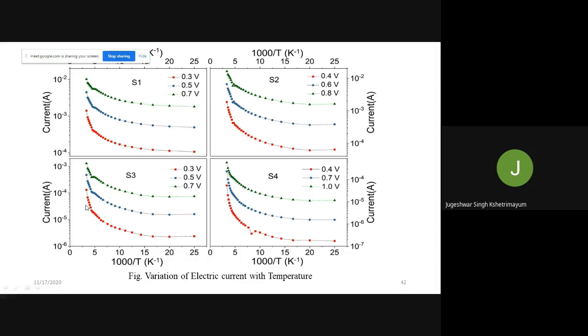The presence of both extended and localized states might give rise to different conduction mechanisms. Both are contributing in the conduction mechanism. At higher temperature region, the excitation of carriers from the localized state to the extended state increases, and so does the carrier density at the extended state, which ultimately increases the current.